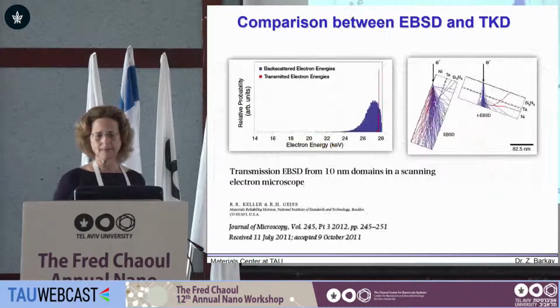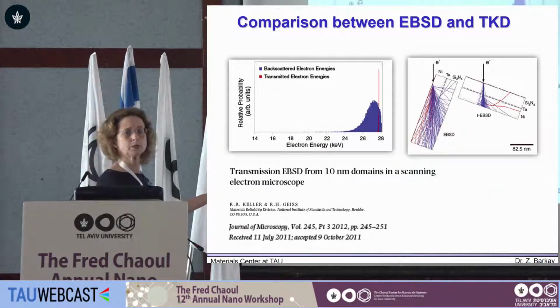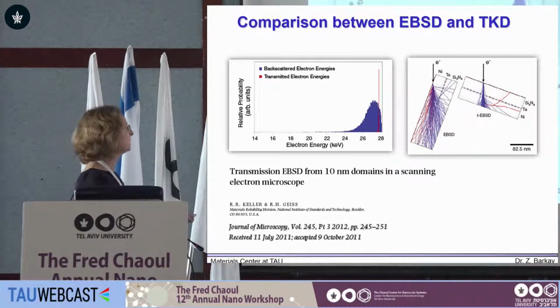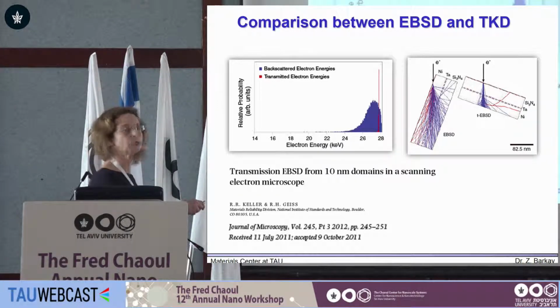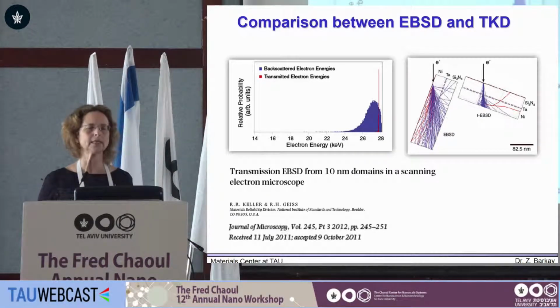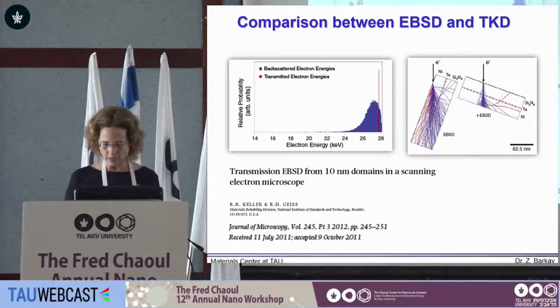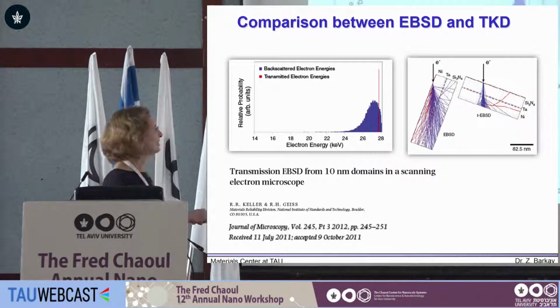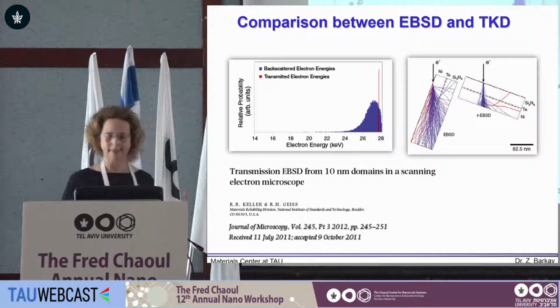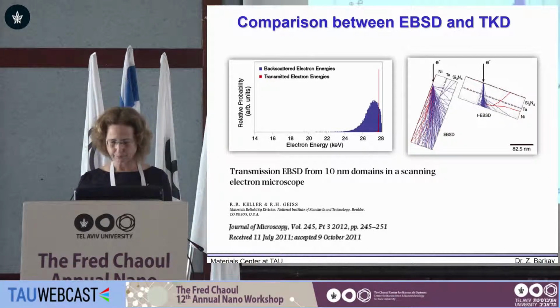What we gain by that is much better resolution. Why? Because if you look at the two different configurations, you see much more scattering in the EBSD than in the TKD, and we can also see that the intensity electron distribution is much more sharp and defined for the TKD orientation. This explains why we have much better resolution in this configuration, which is attributed to the fact that we have a thin film and a low tilt angle in orientation.